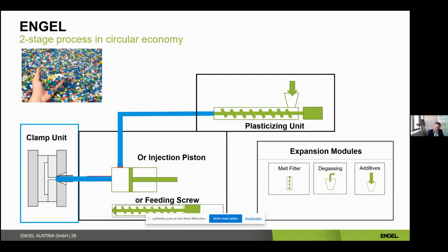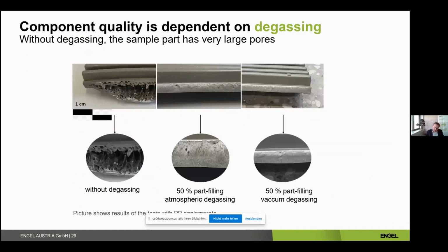And I just want to show you one result that we achieved with the venting. This picture is from our development department, which makes some analysis of the venting ability on an injection molding machine. And this shows on the left-hand side a part which was not vented. It was with roughly 1% of moisture. We put the moisture in with natural fibers in order to have a proper distribution of this moisture in the material, and then we realize there is a big foaming.